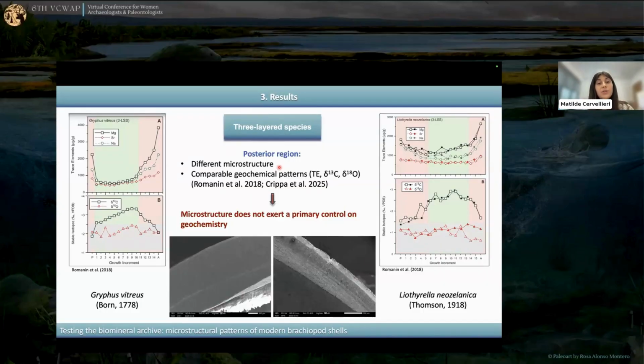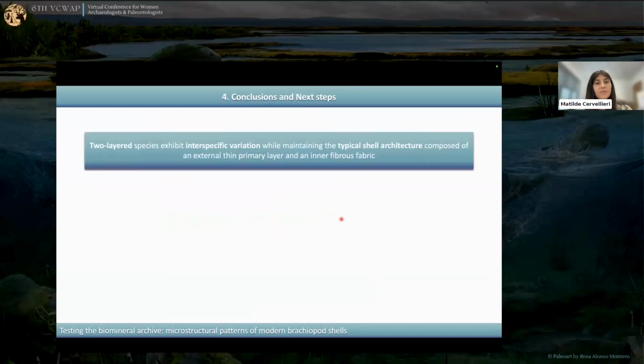However, it has been reported in literature that there are comparable geochemical patterns between the two species, in particular a U-shaped trend for trace elements and a reversed U-shaped trend for carbon isotopes. But having said that, the microstructure is different in the posterior region, so my consideration for now is that microstructure does not exert a primary control on geochemistry. However, I will further explore this relationship by doing high resolution geochemical analysis using a laser ablation system in order to target the different microstructures of the shell.